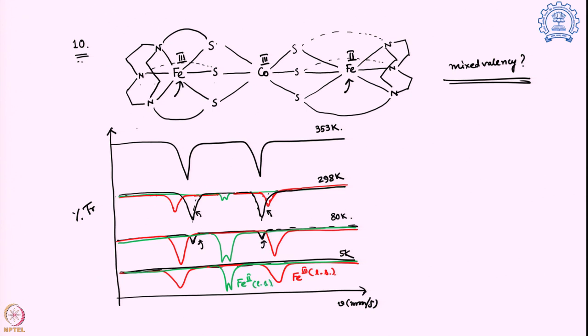So why is there a shift in the quadrupolar splitting? Because this one is very little split, while the red one is quite highly split. Why is it happening? That actually depends on the splitting energy. So this one is quite close to an octahedral geometry, and the same thing is happening for the iron 3. Let us see what is actually happening between iron 3 versus iron 2.